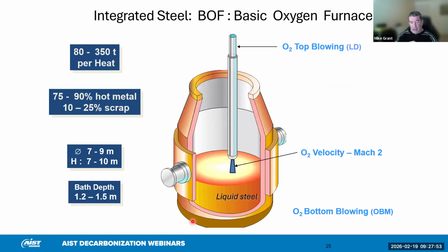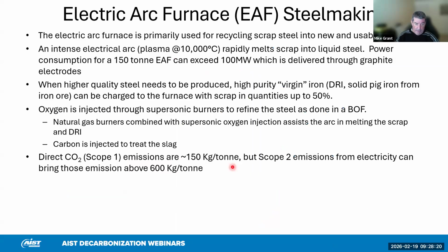This is a basic oxygen furnace. It's not a really complicated vessel. The scrap and the hot metal are charged into the bottle-like vessel. This lance delivers supersonic oxygen at Mach 2, two times the speed of sound, to vigorously burn out the carbon and the residual elements from the process. So that's the basic oxygen furnace, the classical steelmaking process.